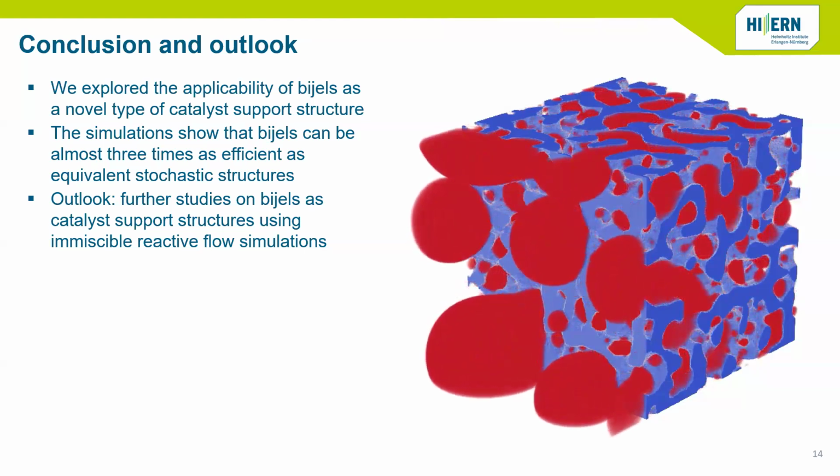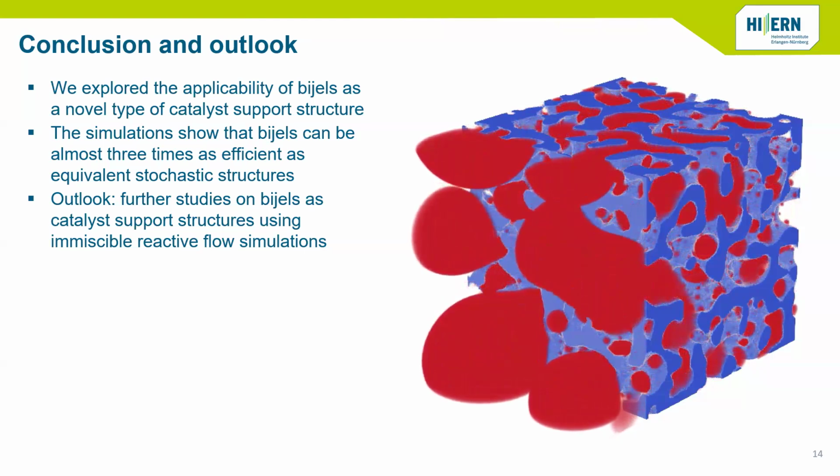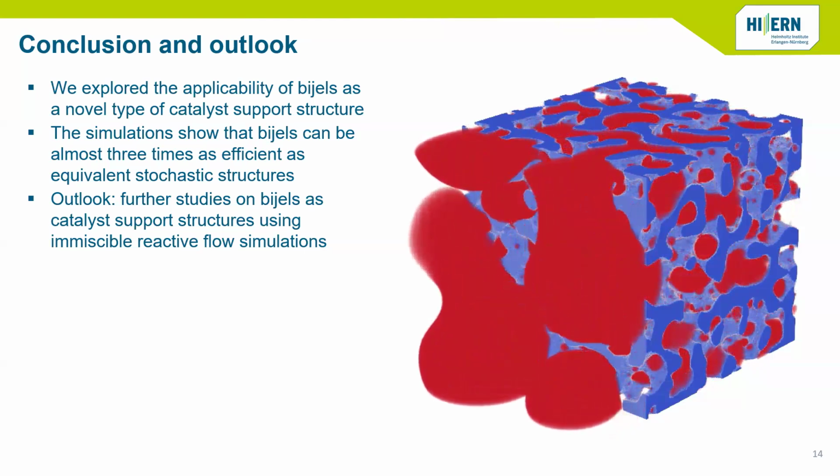How did you generate these structures? Was it just simple overlapping spheres? Yeah, we basically made an algorithm to optimize the porosity and the surface area of the stochastic structures at the same time. So it's just overlapping spheres where we can compute the porosity and the surface area and then keep on iterating until we converge towards the values that we would like to have.